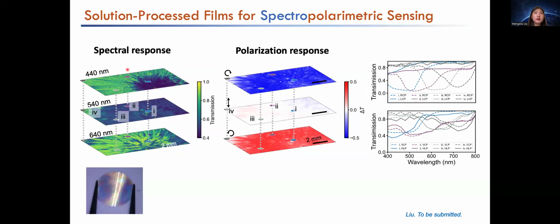If we look at a disordered film we created, for the spectral response, we have very different spectral patterns for the single film with different wavelengths of light. So we can get a very unique pattern from each of the wavelengths. And also for different polarizations, we get completely different patterns. This is simply by introducing disorder into this perfect helical structure.